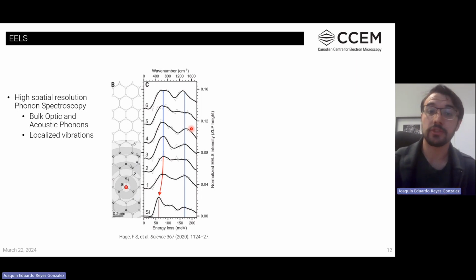Until it becomes more constant or bulk-like as we go further away. As you can see, this kind of vibrational mode is really sensitive, confined to just a few atoms or atomic layers apart from the system, so that already at the 6th atom, the presence of the silicon seems not perceived by the last carbon atom.